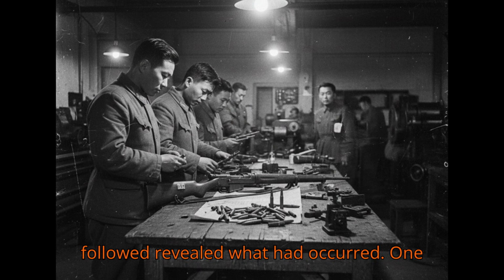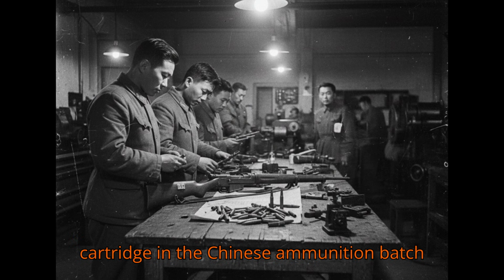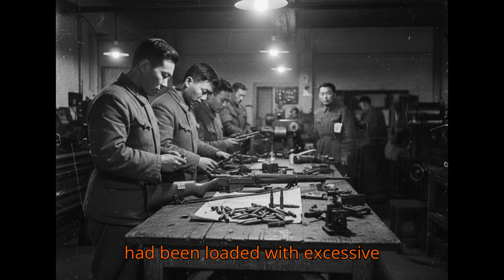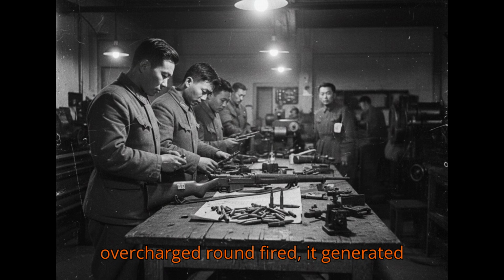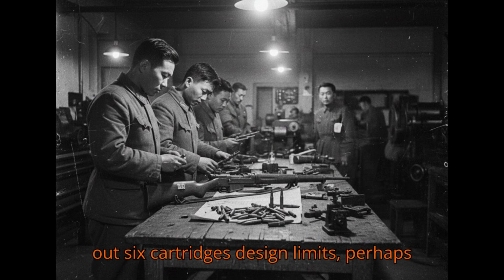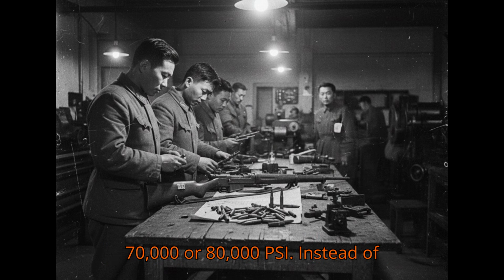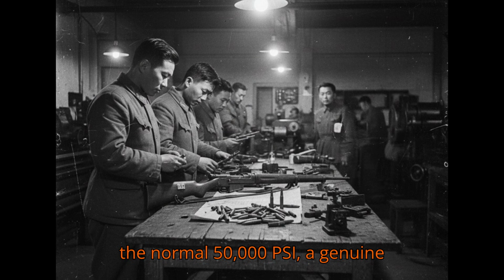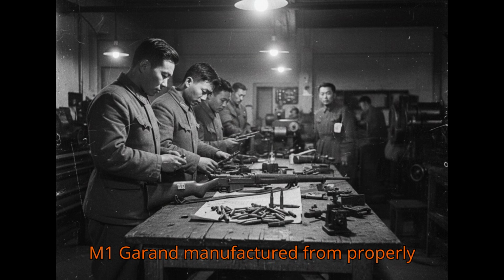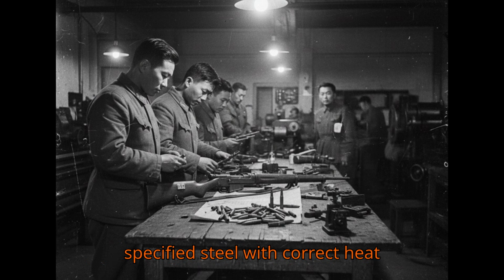The investigation that followed revealed what had occurred. One cartridge in the Chinese ammunition batch had been loaded with excessive propellant, a quality control failure in the ammunition factory. When this overcharged round fired, it generated chamber pressures far exceeding the .30-06 cartridge's design limits, perhaps 70,000 or 80,000 psi instead of the normal 50,000 psi. A genuine M1 Garand, manufactured from properly specified steel with correct heat treatment, might have survived this overpressure event with damage but without catastrophic failure.